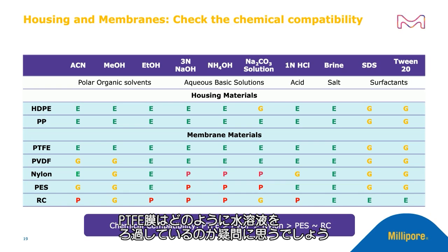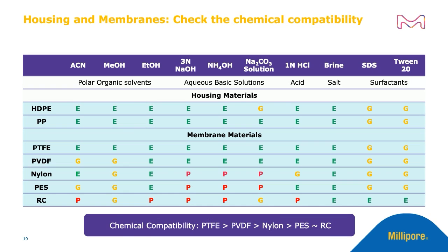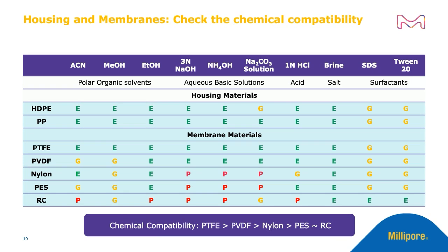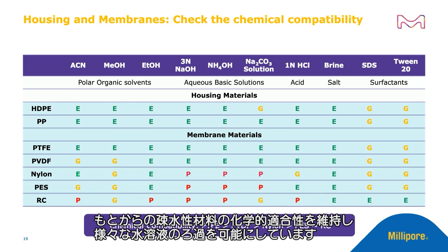You might wonder here how the PTFE membrane is able to filter aqueous solutions. The PTFE membrane that we are talking about is Millipore Sigma's hydrophilic PTFE membrane. A PTFE or Teflon membrane has very high chemical compatibility and is compatible with a wide range of chemicals, but it is also hydrophobic in nature. What we do within Millipore Sigma is create a hydrophilization treatment for this PTFE membrane, which retains the chemical compatibility behavior of the original hydrophobic material, but allows filtration of various aqueous solutions. So this hydrophilic PTFE membrane has the highest chemical compatibility of all the various membranes studied.